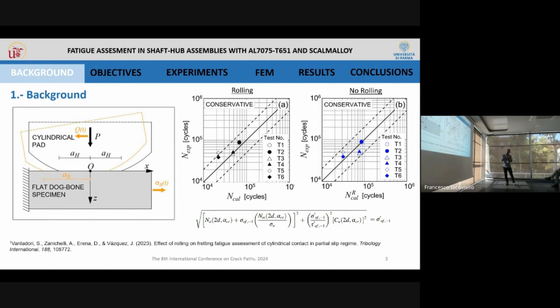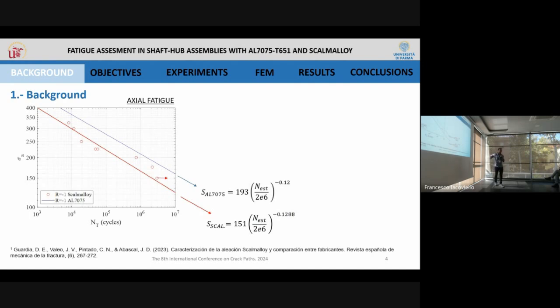Obviously, to apply this criterion, we need the typical fatigue properties and also the fatigue curve. For the case of aluminum 7075, the fatigue curve is well described. You can find it in the literature, so no more comments on this curve. We have chosen one of them. On the other hand, we need the fatigue curve of the Scalmalloy. The good thing is that we have our own fatigue curve with specimens made by the same manufacturer that will manufacture our cells, thus eliminating one possible variable of the problem.